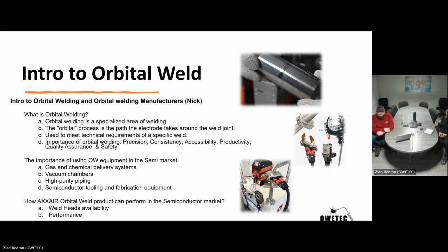So there's a mode in the power supply that you can pulse. You can rotate the tungsten on the pulse basically, so you stay longer on your welding joint. So you rotate slower and you create more heat. And also there is gas, right? You can use a mix of gas, and this becomes the next step over the welding, but it's possible to an extent. Then we're talking about pipe welding, right?